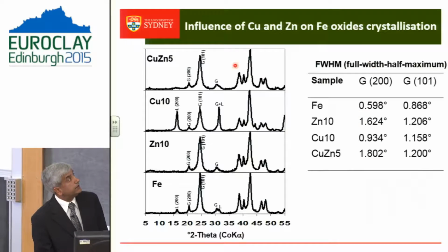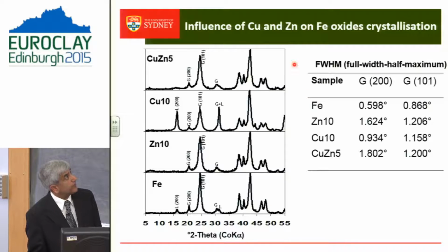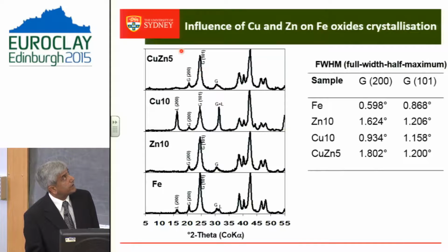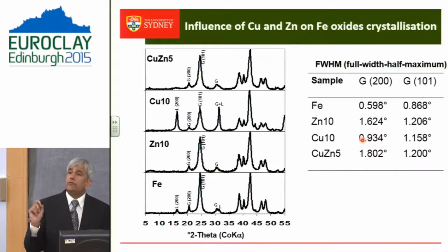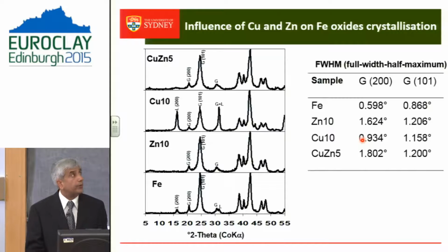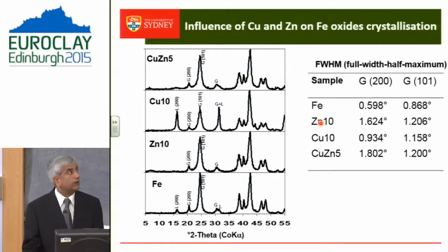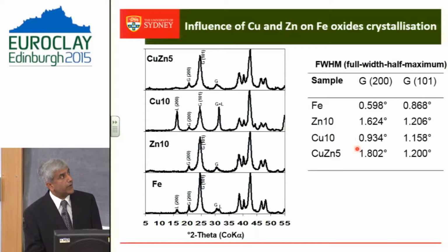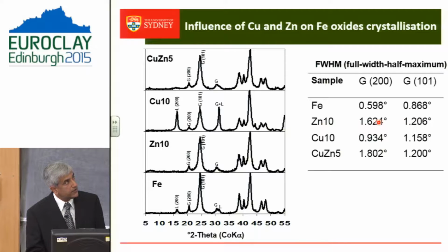If you look at the diffraction pattern of the final product in the presence of zinc, copper, and copper and zinc together: zinc gives pure goethite, copper gives a fair bit of lepidocrocite, and copper and zinc together give goethite. As we saw in case of the pure system of copper, although we are saying here this is the nominal amount, 10 mole%, this didn't go in the structure of the mineral. Only a small amount of copper went in the structure, and that's why the widths are not affected as much as they are in case of zinc.